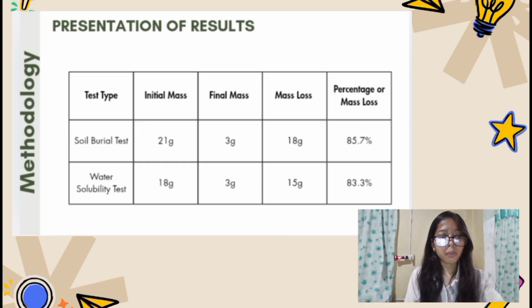While in the water solubility test, the sample started with an initial mass of 18 grams and decreased to 3 grams. This reflects a mass loss of 15 grams or an 83.3% dissolution rate when exposed to water. Both tests indicate a high level of environmental breakdown, with over 80% of the material's mass being lost in both terrestrial and aquatic simulations.